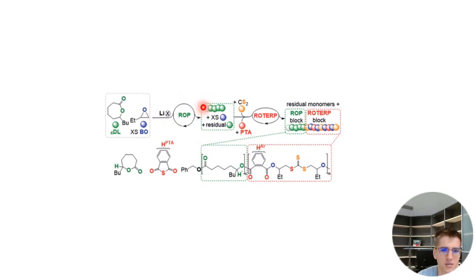And what happens is that you do ring opening polymerization of the lactone, here in this case epsilon decalactone. Why did I use epsilon decalactone? Because it was very established for this type of catalysis, and it gave good control, nice dispersities. I didn't try this with lactide and lithium salts, but there's work from Waymouth showing that lactide needs more complex catalysts, not super complex. Here you're just using lithium salts and epsilon decalactone. This was reasonably controlled, so I went with it. And you can do this in epoxides without any of the epoxide polymerizing.